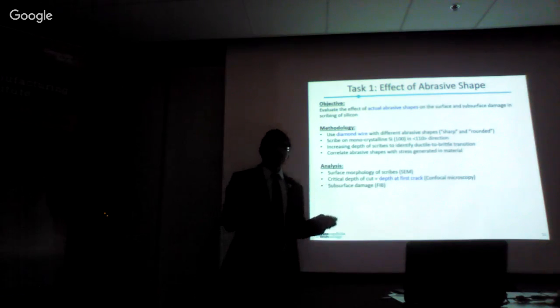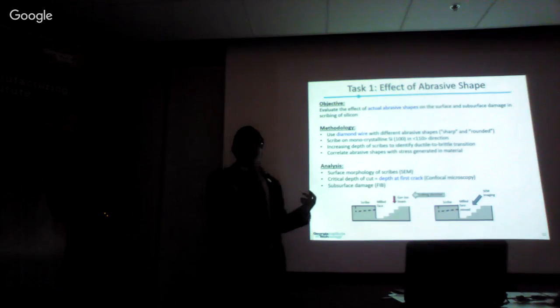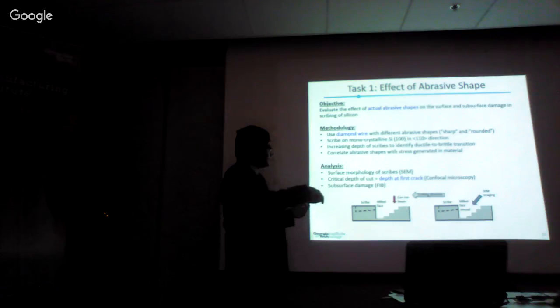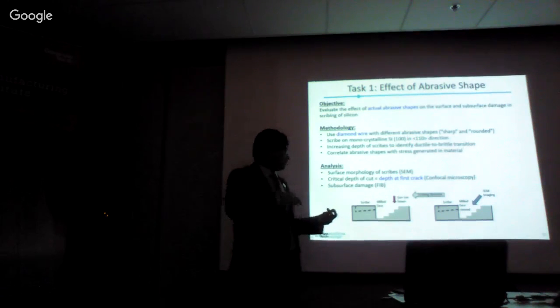We analyze the scribes and the grooves by seeing the surface morphology of the scribes using SEM. Then we find the critical depth of cut, which is the depth of the groove at which the first crack appears, by confocal microscopy. And finally, for the subsurface damage, we use a focused ion beam technique where you see here, there is a gallium ion beam which is used to mill the face perpendicular to a scribe. This is the scribing direction. And then we can view the milled surface, the cross section of the silicon under the scribe, and find what is the damage in the subsurface.